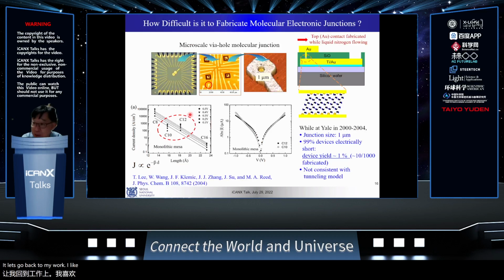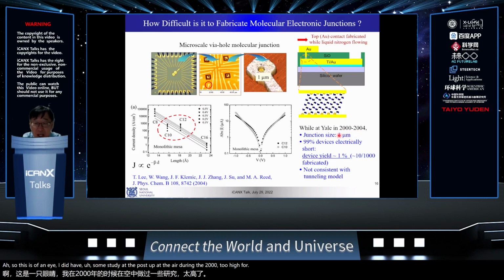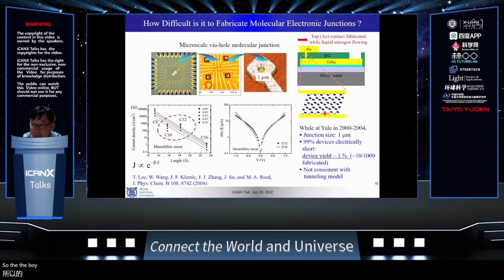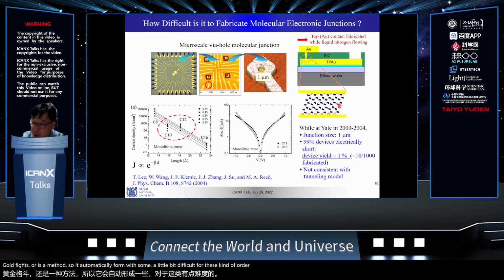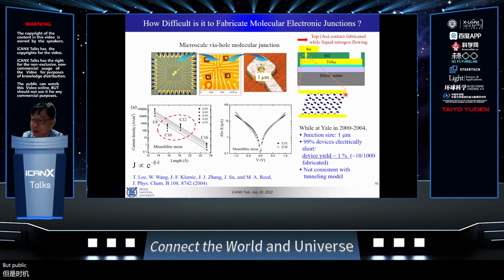So I gave about 20 minutes of background. This is where I did some study as a postdoc at Yale during 2004. And I already told you that it's very difficult to fabricate the junction. The reason is that it is so thin. So the molecule can self-assemble on the bottom gold by a solution method. So it automatically forms, with a little bit of defect, but it's kind of an ordered structure. But the top electrode, you have to provide the top electrode.